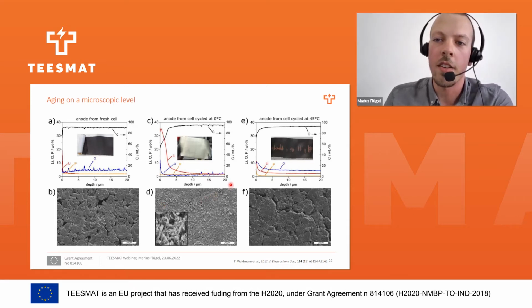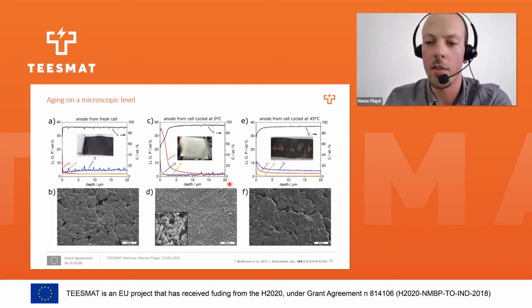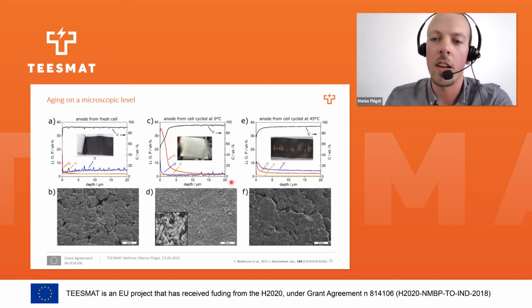After cycling at high temperatures, which leads to a heavy SEI formation, we still can see the graphite particles. However, due to the SEI film, the smaller particles are not distinguishable anymore. And with GD-OES depth profiling, we see an increased amount of lithium in the anode.